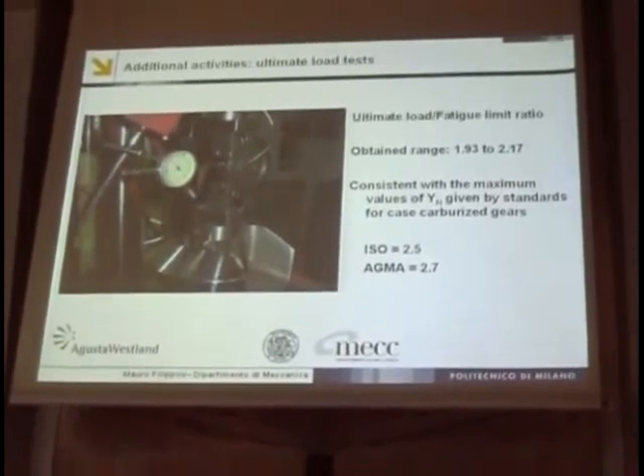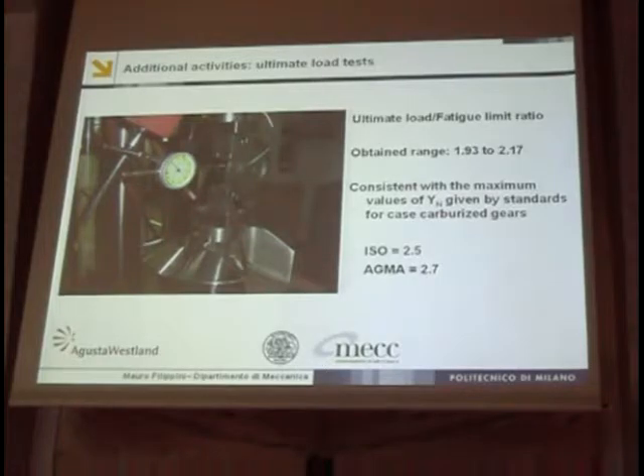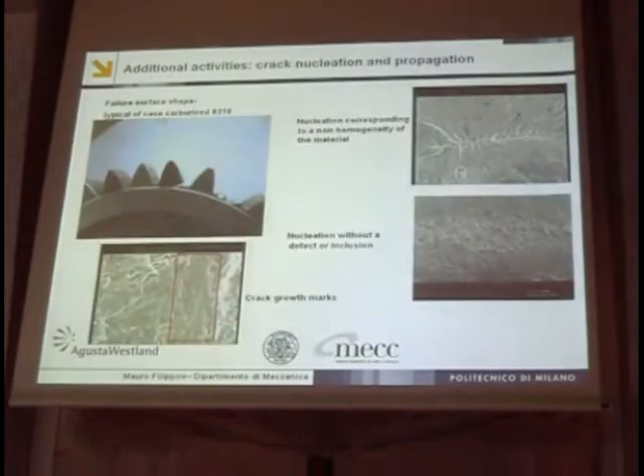So, as I told you, we also performed an ultimate load test because there is a need in the rating standard to consider the ratio between the ultimate load and the fatigue limit. This is a parameter for the rating standards, and we found figures which are consistent with the current practice and the ISO standards and the AGMA standards.